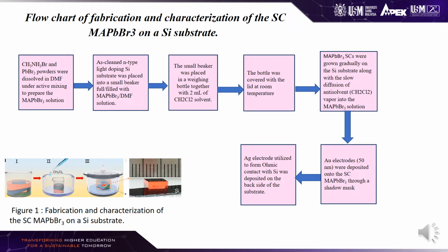This is the flowchart of fabrication and characterization of the single crystal MAPbBr3 on a silicon substrate. The first step is that CH3NH3Br and PbBr2 powders were dissolved in DMF under active mixing to prepare the MAPbBr3 solution. A clean n-type doped silicon substrate was placed into a small beaker fully filled with the MAPbBr3 DMF solution. The next step is that the small beaker was placed in a weighing bottle together with 2 ml of CH2Cl2 solvent, and then the bottle was covered with the lid at room temperature.